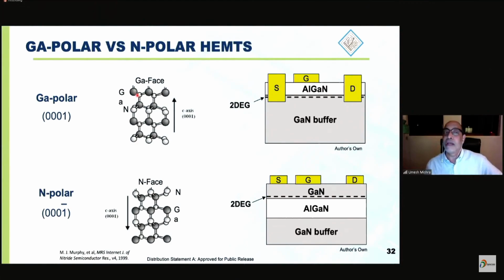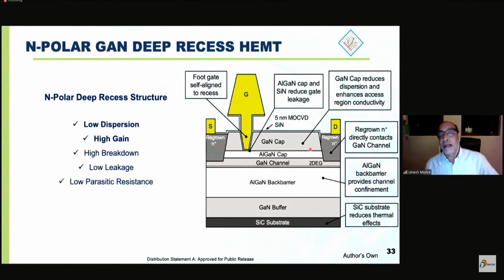So how do you do that? What we developed at UCSB since 2006 is a new form of gallium nitride called nitrogen polar GaN, which is, instead of having AlGaN on top of GaN, we put GaN on top of AlGaN. It's an inverted structure. It's very easy to draw, very hard to do, but we did it over the last 15 years. And these nitrogen polar structures basically have regrown contacts for low resistance, a gallium nitride cap to reduce dispersion.